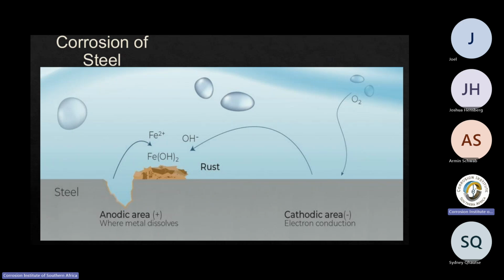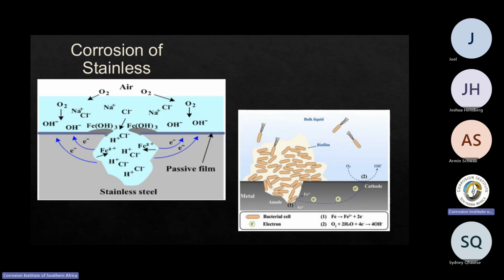But if you have a blob of dirt in one area on top of the steel and your coating doesn't stick there, you've now set up a corrosion cell. And pitting and corrosion starts occurring in that specific area. Or even worse, it starts creeping in underneath the coating and lifts the entire coating off the substrate, which can cause dramatic failures. What about stainless steel?